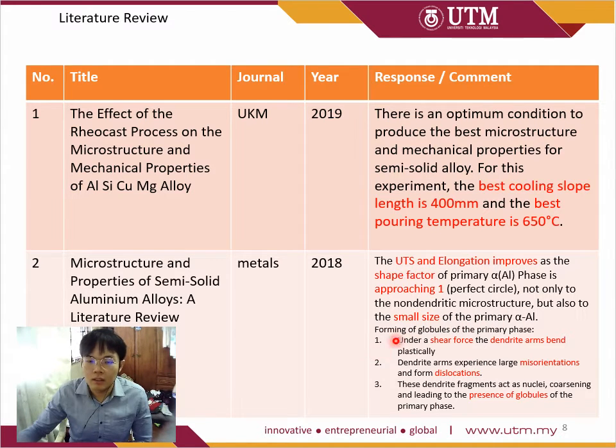And this is the mechanism of forming of globular structure. Under shear force, the dendritic arms bend plastically. The dendrite arms experience large misorientation and form dislocations. And lastly, these dendrite fragments act as nuclei, leading to the presence of globular structure of the primary phase.